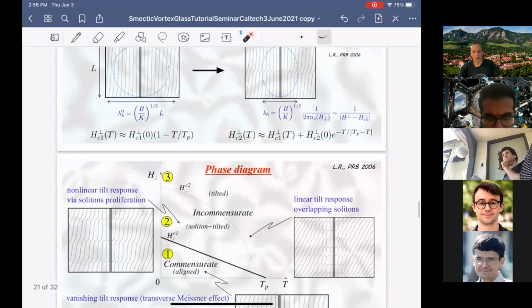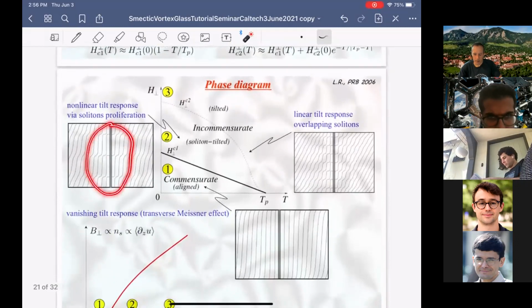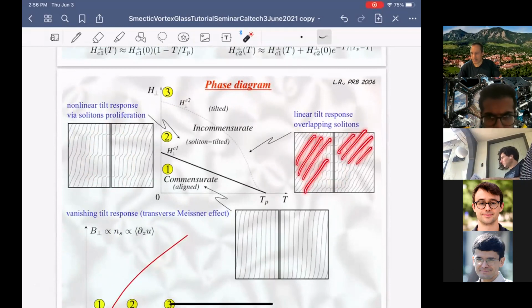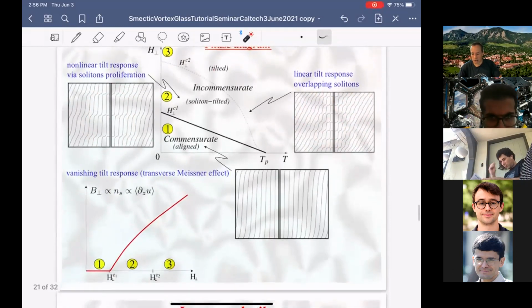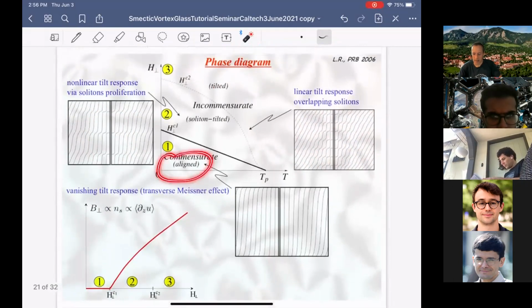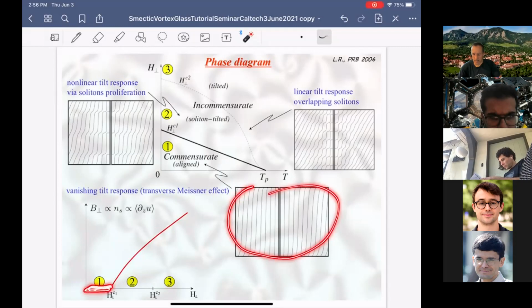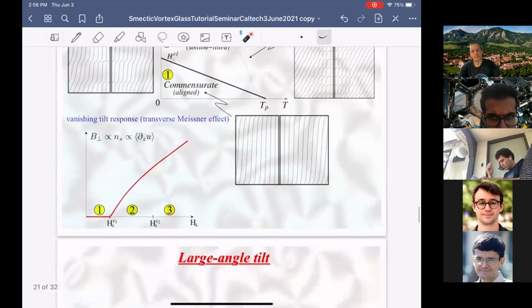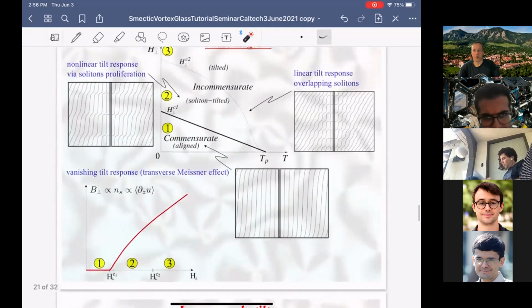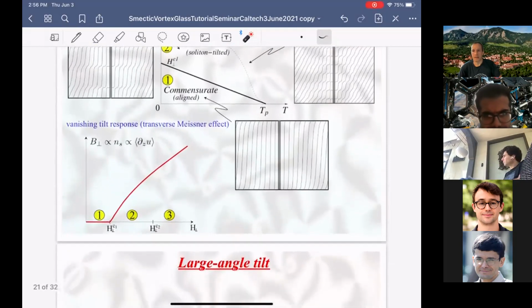As you push further, more solitons develop, and eventually they begin to overlap, and now you have a smooth tilting, except right near the columnar defect. So there's this phase diagram that I developed. There's a commensurate phase, incommensurate tilting phase, and then the fully tilted phase. So you go from here, that's like the Meissner phase for tilting. That's the analog of Bose glass for one column. Then solitons enter in this really correlated way. And then finally they overlap, so you get to this thing. Okay, so that's, again, still a little bit of background, but I think that's still an interesting story.